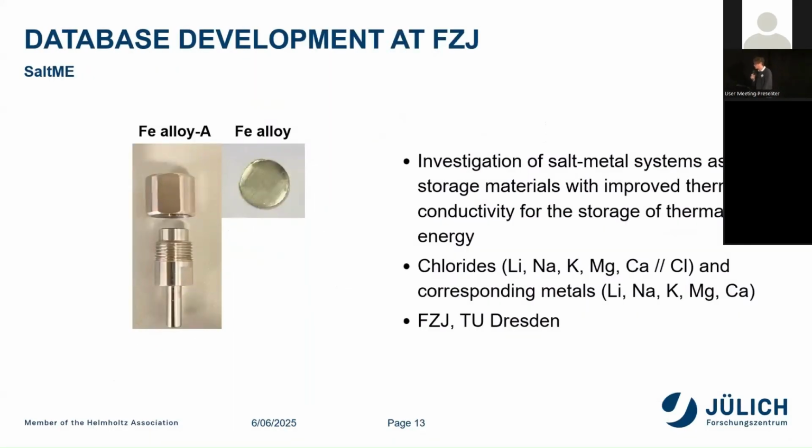So the last thermal storage project I wanted to talk about was the SaltMe project. While the other projects mainly investigated salt-based materials, this one looks at salt and metal combinations. One of the drawbacks of salt-based thermal storage systems is that the thermal conductivity or thermal diffusivity is relatively low. But it's hoped that by adding a metal to this system, we can increase this thermal conductivity and have more efficient thermal storage systems.